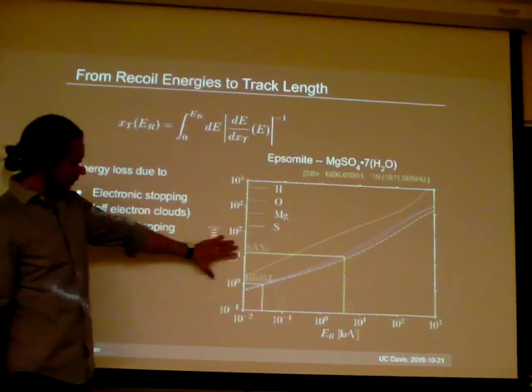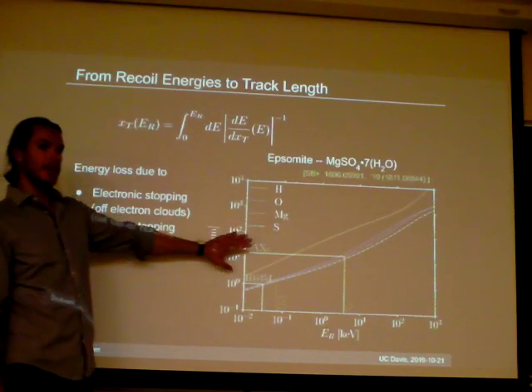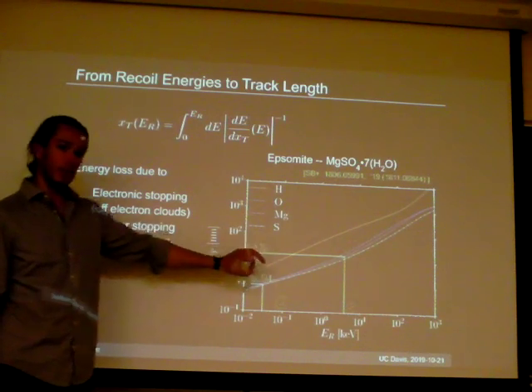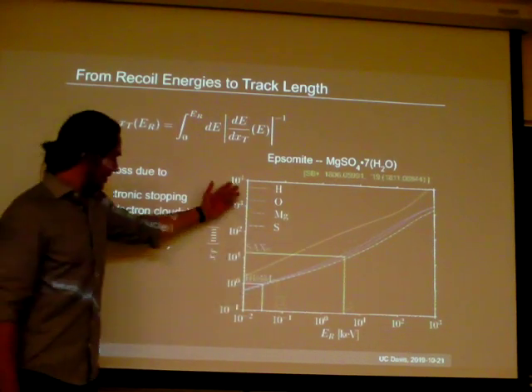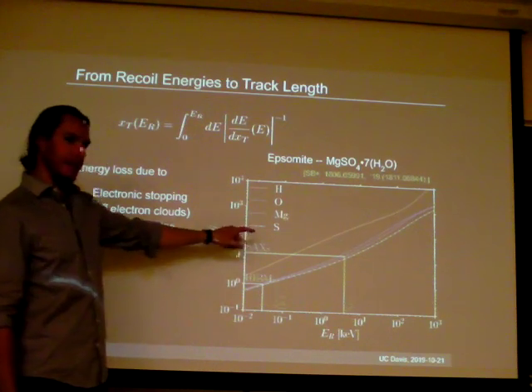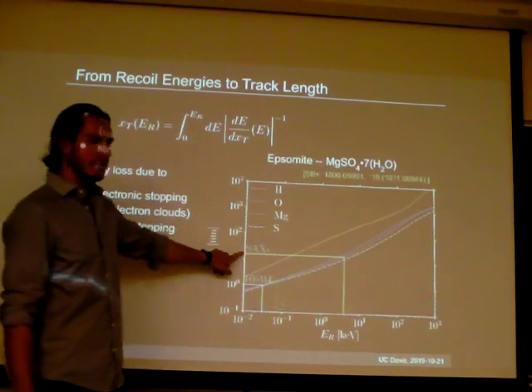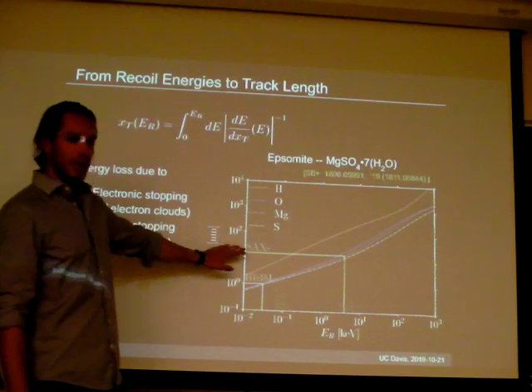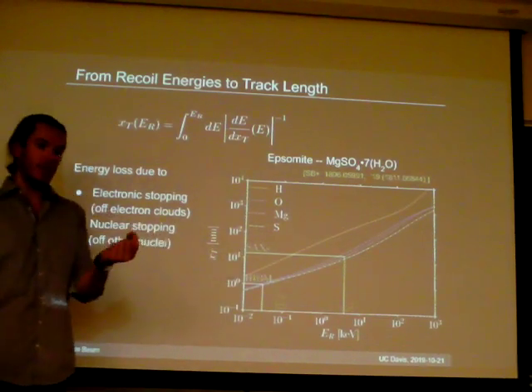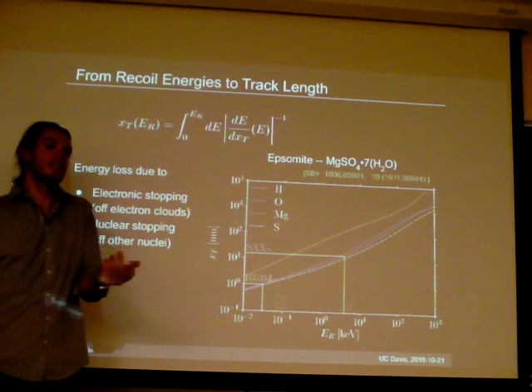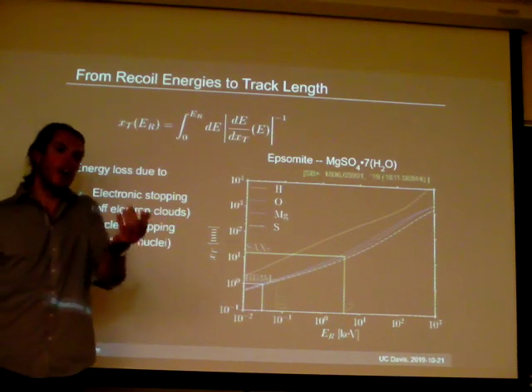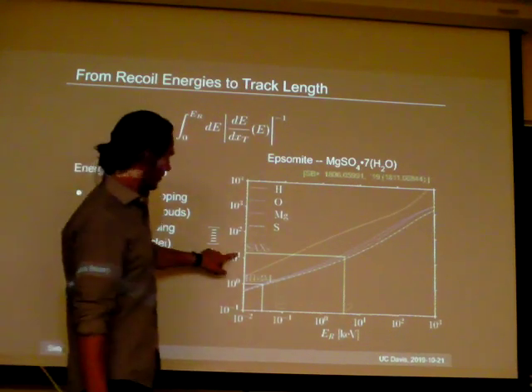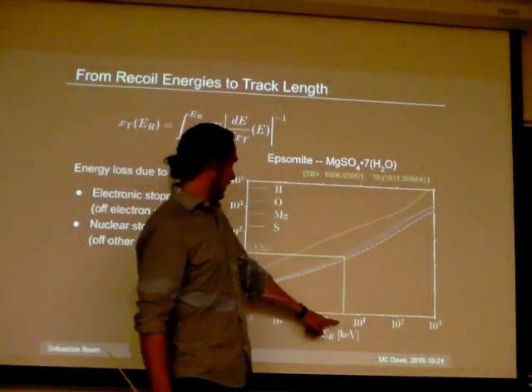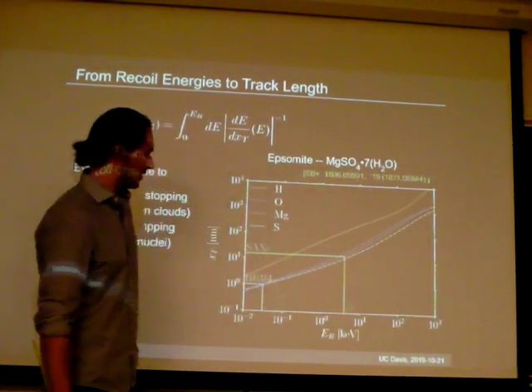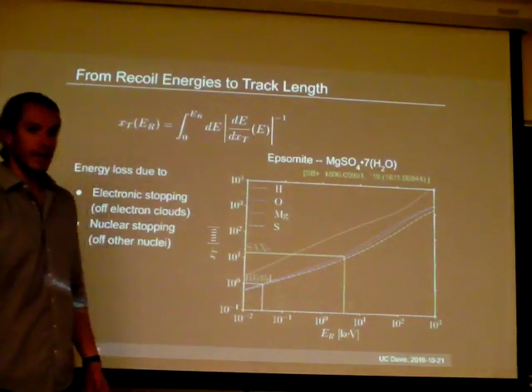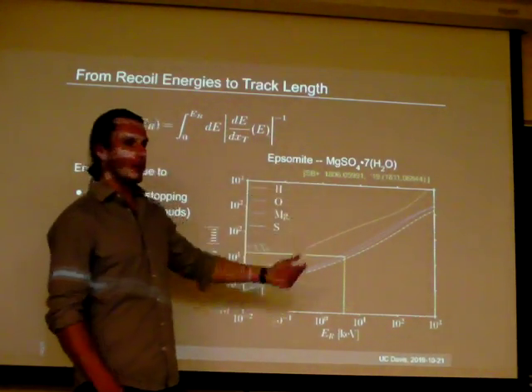The second piece you can read out from this plot is what are the thresholds you're going to be able to achieve. So we put some benchmarks on here. Imagine you have, and I'm going to tell you later how this works, some form of X-ray microscopy where we think you should be able to get a spatial resolution of your tracks of something like 50 nanometers, which roughly tells you the shortest tracks you're going to be able to read out are like 50 nanometers long. And so now you just follow your line and you end down, okay, so this corresponds to recoil energies of a few keV, 3-4 keV in this material, but it's an order 1 change to go to any other material.